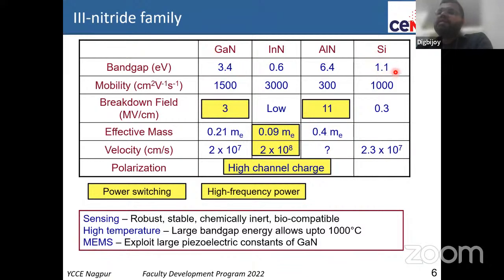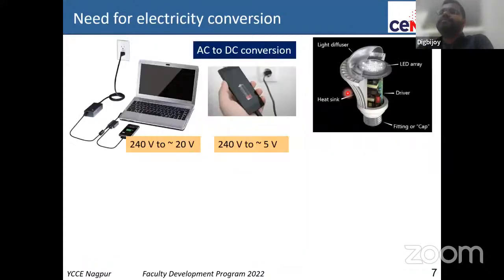For instance, if you take a silicon MOSFET, you cannot operate it at very high temperature, like say 500 degrees Celsius or 800 degrees Celsius. It will not work because it will become intrinsic. All of you know it, right? At high temperatures, silicon will lose its semiconducting property, but gallium nitride will not. People have actually experimentally shown that gallium nitride transistor works fine even at 1000 degrees Celsius, which is impossible with silicon. So for high temperature electronics, for radiation hardness, for very hazardous environment, gallium nitride devices can be much more robust and can withstand this hostile kind of temperature and situations than silicon. So these make it very interesting actually.